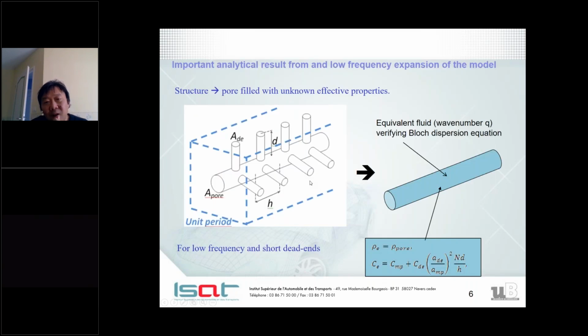A bit more detail on the analytical model, because this will lead us to very simple design formulae. So we have this structure. We have a unit cell that you can stack, with several of these unit periods, to create the material. So everything here in the model is basically modeled as a simple perforation without dead ends, but with equivalent properties.